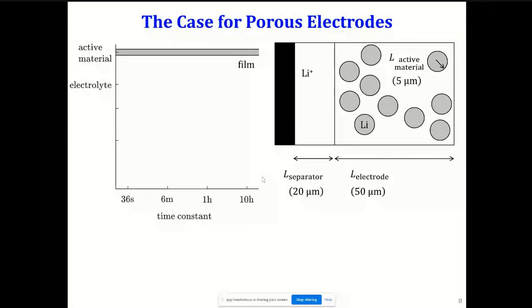Now let's do something else. If the issue was the diffusion length in the solid, how about I break down the film electrode and make it into spheres? Now suddenly my diffusion length for lithium decreases, and it just has to diffuse to these small particles. And correspondingly, the time constant would decrease. It comes out to about 0.7 hours, which is fantastic, right?